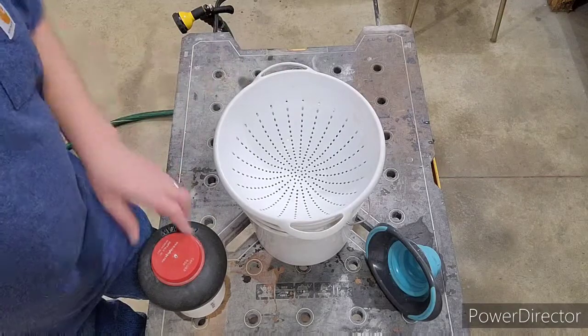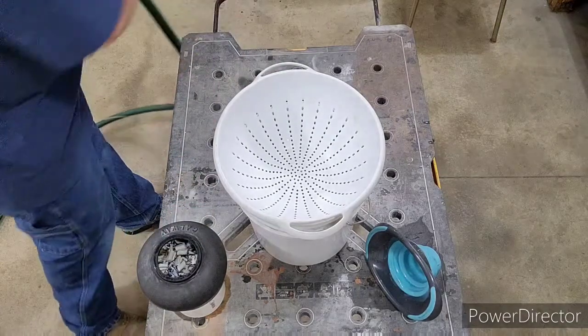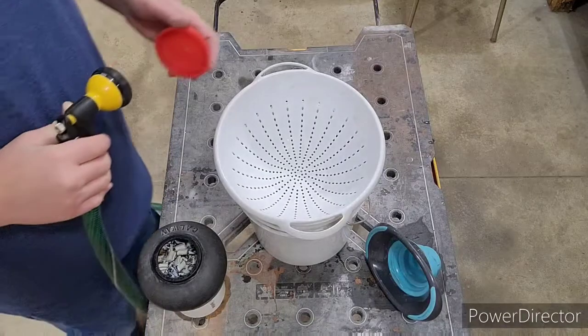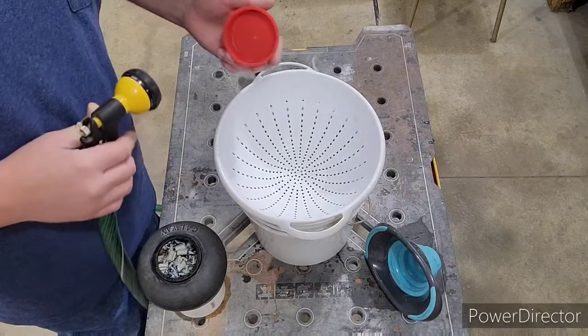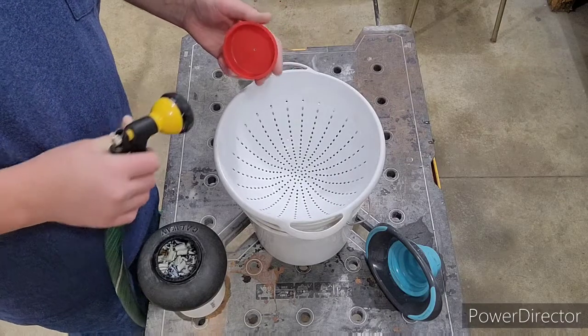Blue Tiger Eyes ran for 3 days in the 1000 grit silicon carbide, and I dumped it and rinsed it, and we put it back in with some borax and did a little burnish, little wash cycle, and we're gonna get it cleaned up here and we'll get it going on polish.